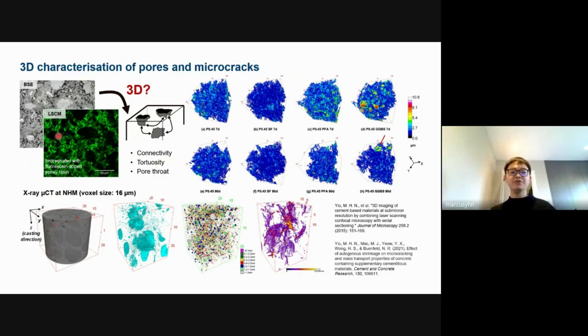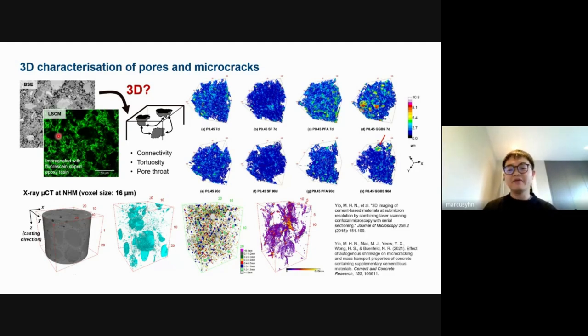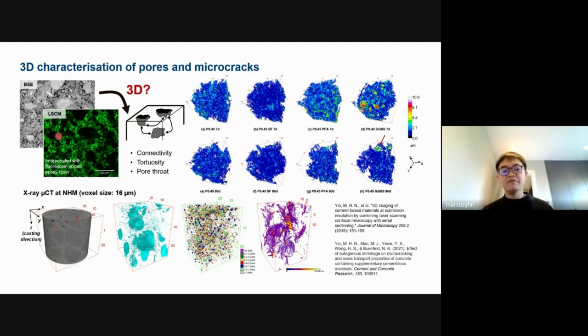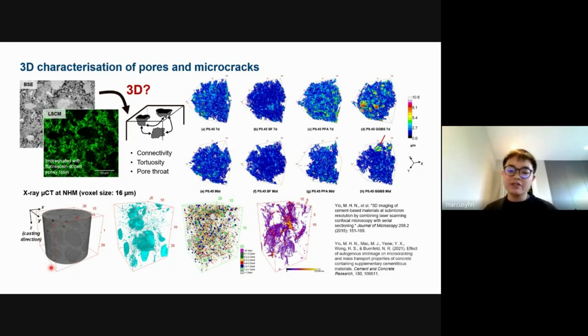What we have seen so far is all limited to 2D. However, the microstructure of concrete and cement-based materials is intrinsically three-dimensional. Although stereology can deduce some 3D information, very important parameters such as pore connectivity and tortuosity, or microcrack length, cannot be meaningfully quantified on 2D images. Therefore, we have also been developing 3D imaging techniques such as laser scanning confocal microscopy and X-ray microtomography to image and quantify pores and microcracks in 3D. This is just a very brief overview; for more detail, please take a look at our papers published in Cement and Concrete Research.